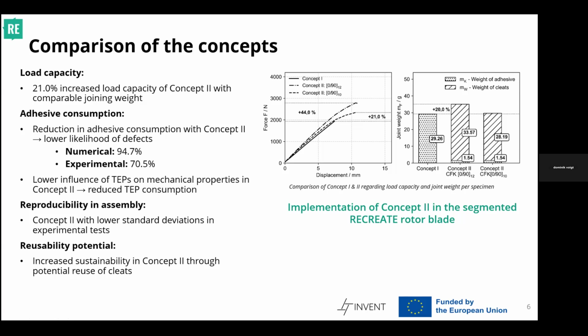Additionally, concept 2 showed improved reproducibility during assembly. This was reflected by lower standard deviation in my experimental tests, which indicates a more stable manufacturing quality of concept 2 in comparison to concept 1. Another point was that concept 2 offers a higher reusability potential, contributing to increased sustainability. This is mainly due to the possibility of reusing cleats after disassembly, after the debonding on demand technology, for maybe other rotor blades or other parts.